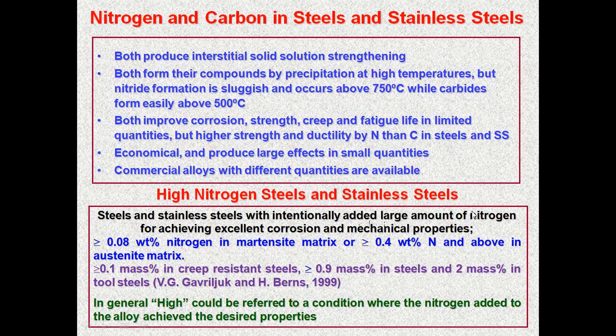Where an intentionally large amount of nitrogen is added to achieve corrosion and mechanical properties. According to the literature, greater than 0.08% nitrogen in martensite, or 0.4% nitrogen and above in the austenitic matrix, gives a wonderful improvement in the mechanical and corrosion properties. In the creep resistant steels, 0.1 mass%, in the tool steels, 2 mass%, and in a normal steel, 0.9 mass% you can add to also get the benefit.